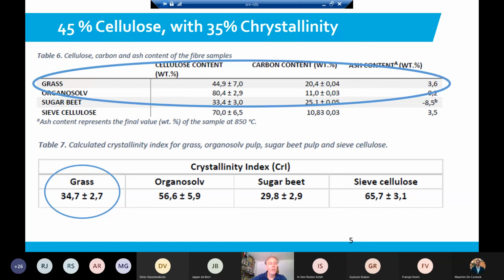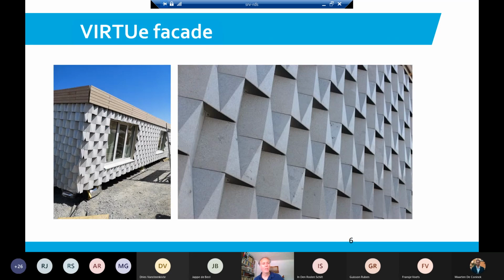And if we look at crystallinity index, then we can see that the grass has a little bit more than 30% crystalline cellulose within it, and that's, for instance, much better than sugar beets. So the value, if you only look at the fiber, will lay between sugar beets and recycled toilet paper from a mechanical point of view.